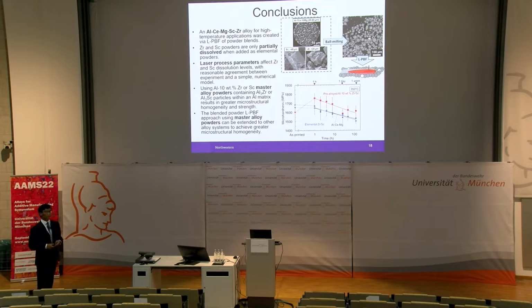So, in summary, we manufactured this aluminum cerium magnesium scandium alloy for high temperature applications by this process of laser powder bed fusion of powder blends. When we use elemental powders, we saw that these powders were only partially dissolved. And then we studied the effect of laser process parameters, such as the scan speed and rescanning strategy, on the zirconium and scandium dissolution levels. And we did this by both experiment and modeling.